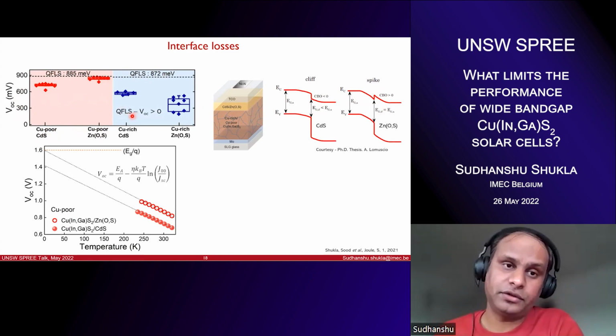If this difference of quasi-Fermi level splitting and the VOC is positive, let's say, you have interface recombination going on. And that's what you see when you look at the copper-rich absorbers. No matter what buffer layer you put, cadmium sulfide or zinc oxysulfide, you always get lower VOC as compared to the QFLS. Even though you expect a spike-type configuration, it doesn't solve the interface recombination problem.